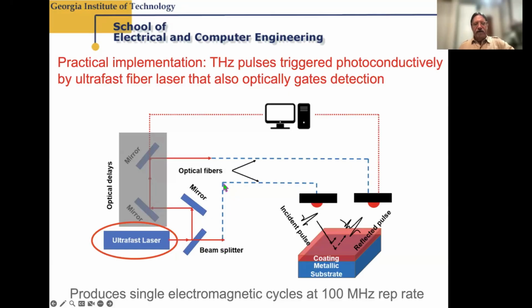So first of all, we generate an optical pulse that is converted into a terahertz pulse, shown here, that impinges upon some sample. So here's a simple case. It's a coating, such as paint, on a metal substrate. When that pulse hits that coating, we're going to get a reflection from the air-coating interface, and then also a reflection from the coating-metal interface below. So the reflected signal is going to have two pulses separated in time, determined by the thickness of that coating.